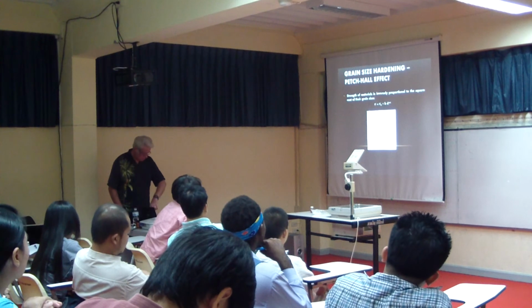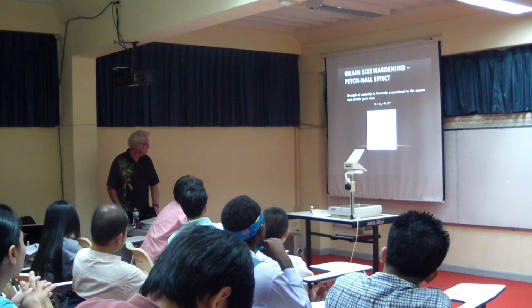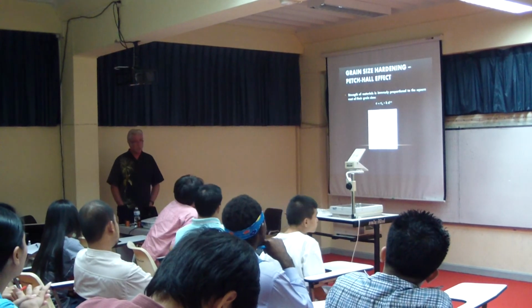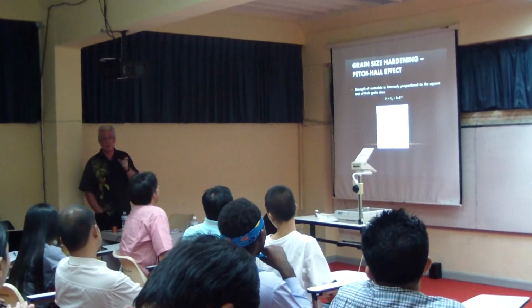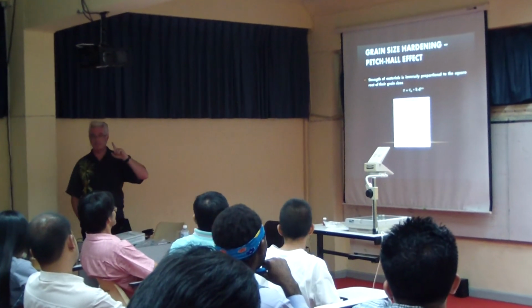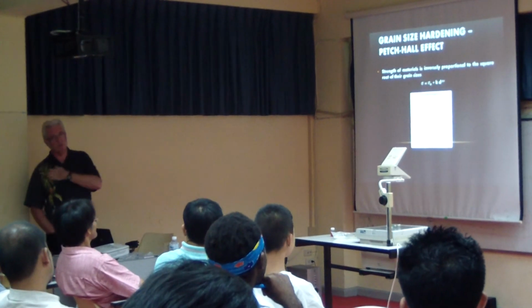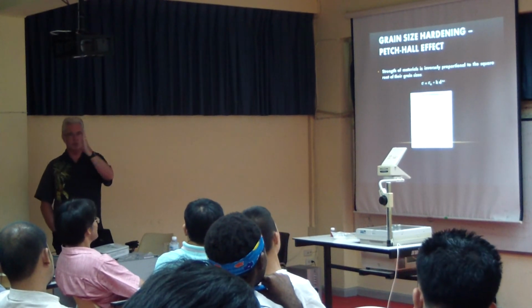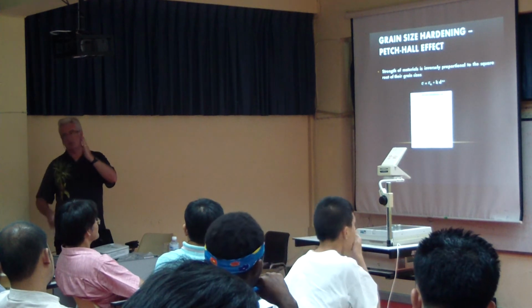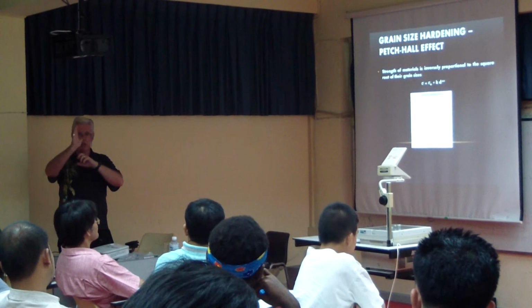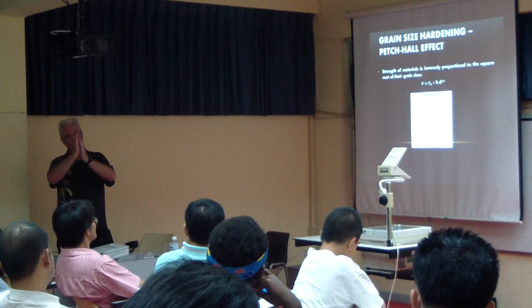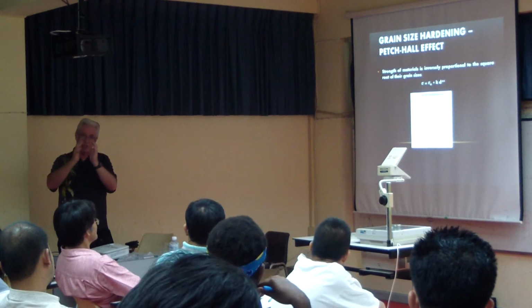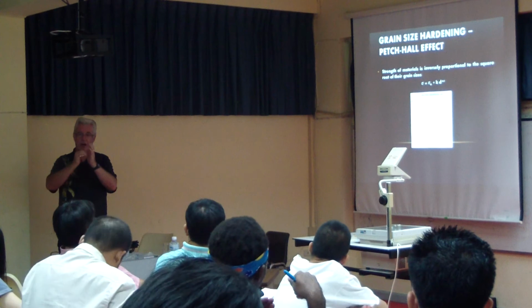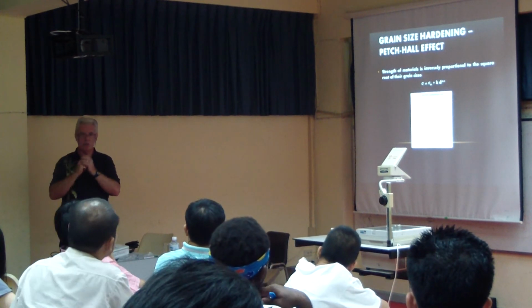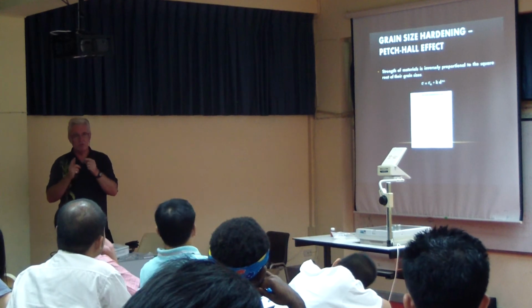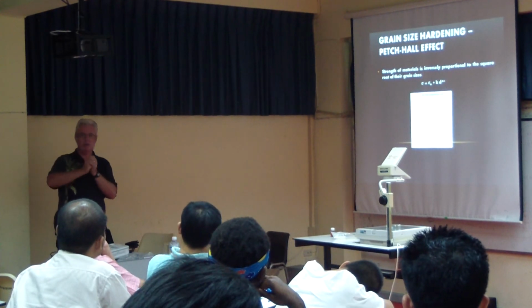To finish off here, I think, looking at these nanocrystalline materials. If I take a metal and reduce the crystal size, generally the strength goes up. And the reason is that the strength is sort of dependent on those dislocations moving. As I said earlier, if I distort the lattice, I hinder the dislocation movement. Well, the dislocations can only move to the grain boundary. If the grain boundaries are close together, dislocations can't move very far, and the strength goes up. So everyone thought, wow, let's make nanocrystalline crystals, or grains, and the strength will be huge.